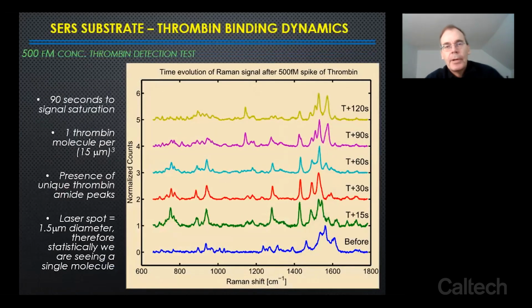We actually tried this out. So we put 500 femtomolar of thrombin into the solution. We start with the thrombin binding aptamer, and after 15 seconds, we started to see a change in that spectrum. And after about 90 seconds, it stabilized into this thrombin plus the binding aptamer spectrum.